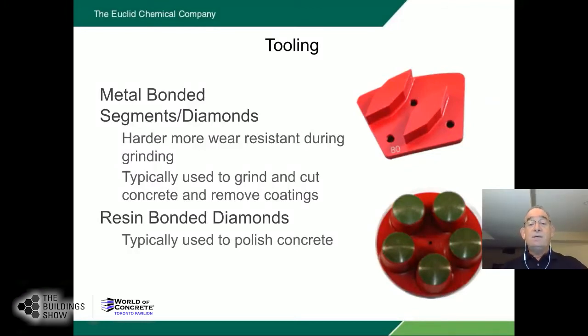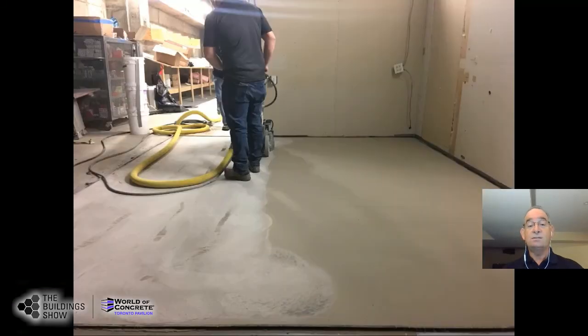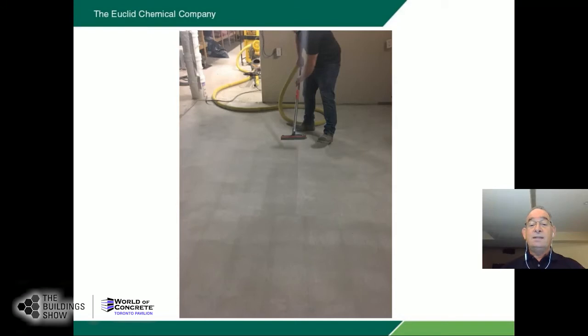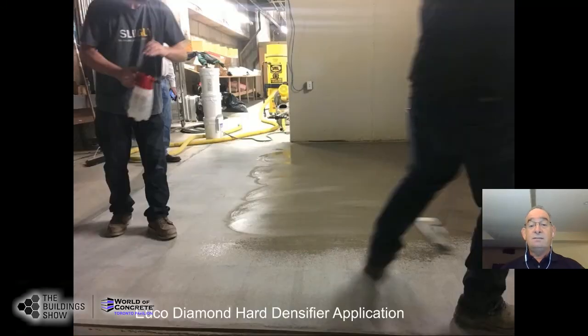So the metal bonds are the ones used for the initial grinding and removing some of that surface in order to expose the aggregate in the case of the PC Ag. And then we switch to the resin bonds from there, which is used for the polishing process to make it as shiny as needed. So here's the material being polished again, starting with something like a 200 grit material. In between those operations, it's cleaned.